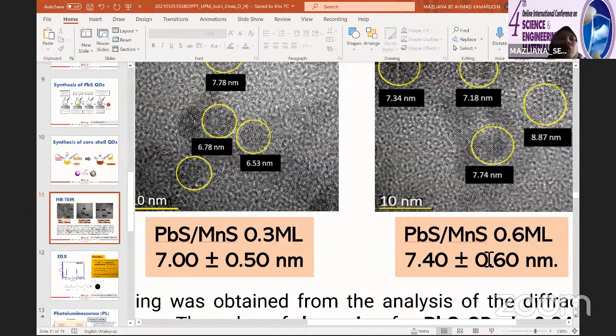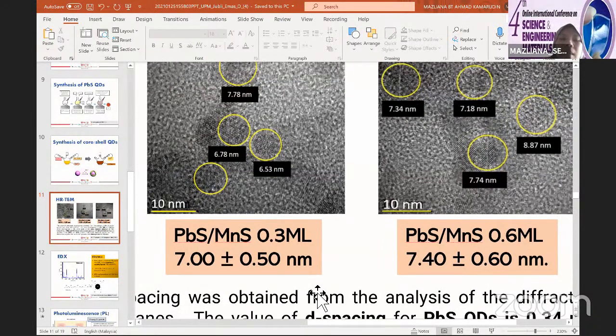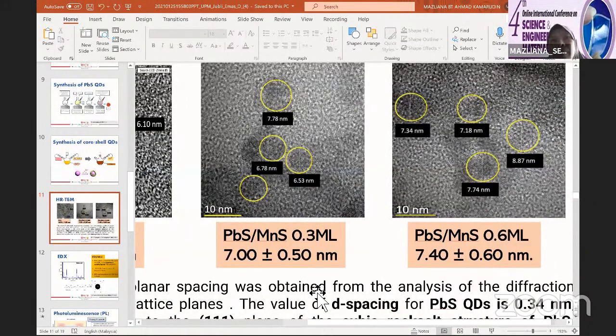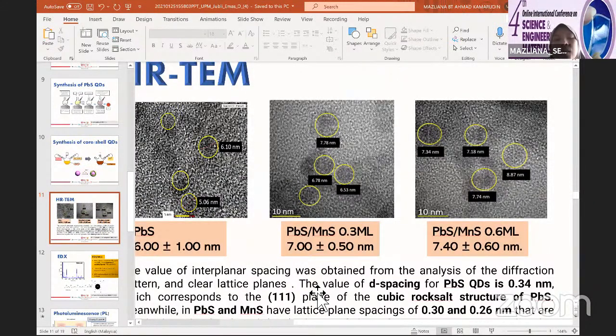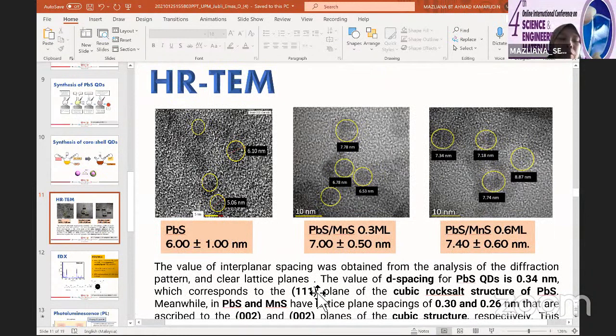All right, okay. So here, why do people grow the core shell quantum dots? Because if you grow the core only, the bare core without the shell, people try to tune the energy. So for example, we managed to get the recipe to produce PbS quantum dot, but then the size that we get is only 6 nanometer. And we try to reduce the size further and further in order for us to tune the energy.